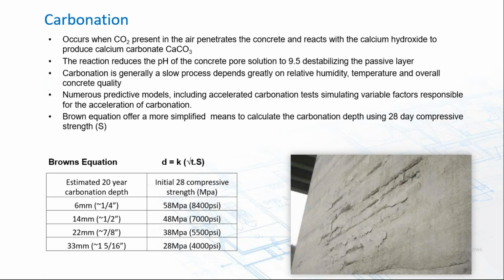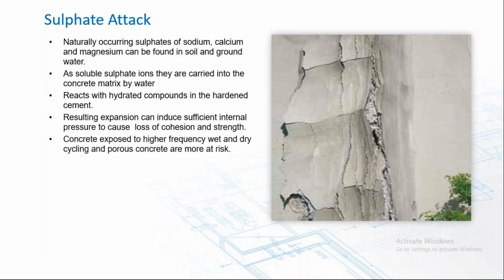And if that was the only thing that happened to concrete, yeah, that's a fairly durable life cycle of a concrete structure. But we're talking about a cumulative effect of a number of other deterioration effects as well. Sulfate attack occurs when naturally occurring sulfates of sodium, calcium, magnesium can be found in the soil and groundwater. And as soluble ions, they're carried into the concrete matrix by water. That reacts with the hydrated compounds in the hardened cement and expands, and that can produce sufficient internal pressure that it can cause a loss of cohesion and strength. Concrete exposed to a higher frequency of wet and dry cycling and porous concrete is much more at risk.